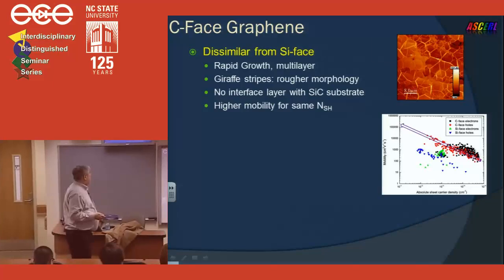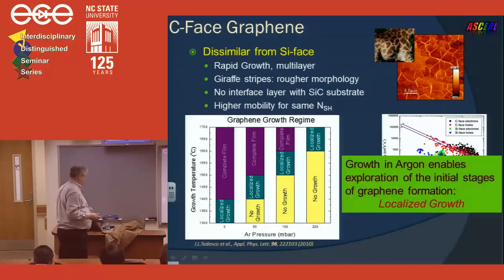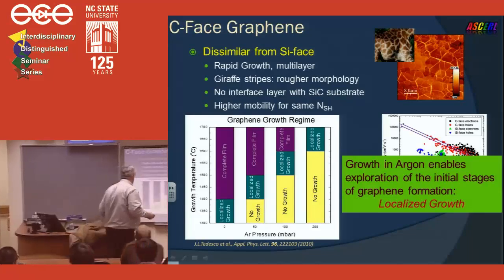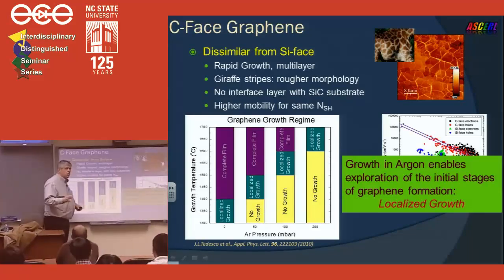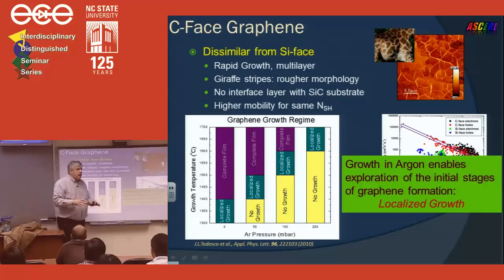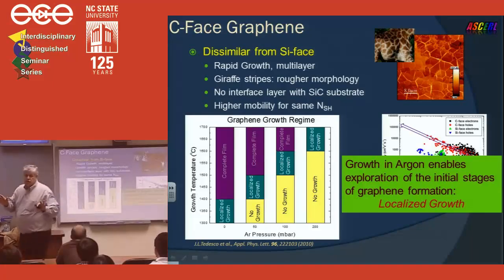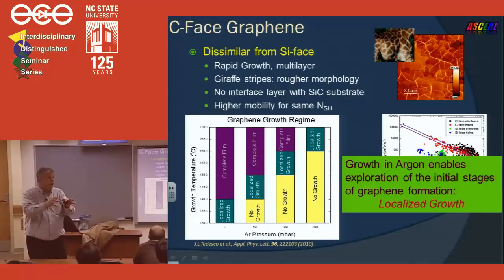So the approach that's being done here, we make use of a very interesting growth mechanism that Joe Tedesco figured out: when you change the pressure in the ambient during the graphene growth, you can have parameters where there's no growth of graphene, and you can have parameters where there's continuous films, and in between you can dial in conditions where you just have localized formation of graphene. And so that means I can now, if you will, freeze the growth and take a snapshot of what's going on when the graphene process just starts.